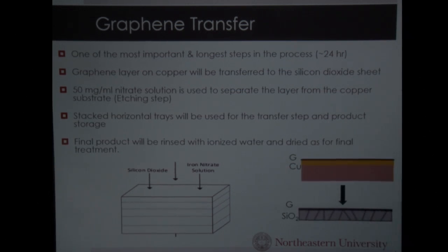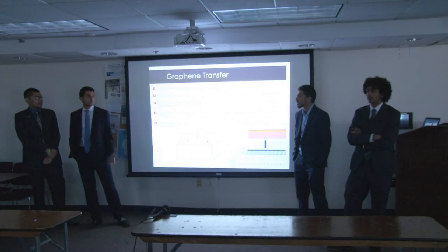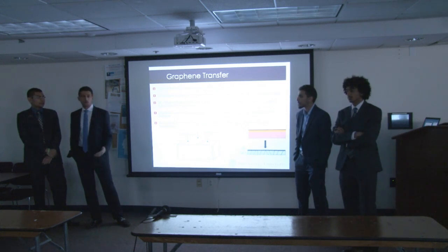How thick of graphene film are you expecting to grow on copper? Yeah, it's in nanometers. I think it's 1.58 nanometers. It's really thin. And they show that you can get a good uniform transfer. Basically, we'll use SEM testing to perfect it. Usually in terms of processes, the average was around 90% to 95%. We estimated that we'll be able to have 93.5%.